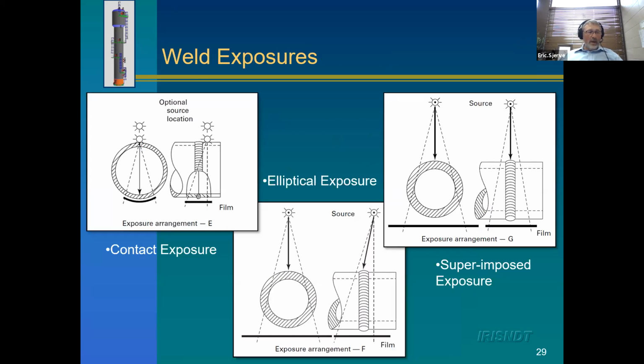With weld exposures, this is the same kind of thing I just showed you. When we're doing welds, we can shoot them with the source right up against the pipe and the film on the far side, which is that contact exposure on the far left. We can also shoot them in either a superimposed or an elliptical exposure, which is when the radiographic source is further away. Typically we do contact exposures for all the bigger diameter pipe and elliptical exposures for the small ones.